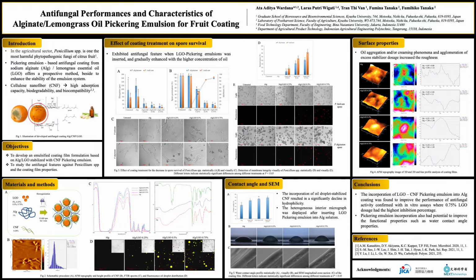Propidium iodide is well known as a fluorescent dye that is able to penetrate dead cells. As seen in figure 3, the result implied that the membrane integrity was impaired by the lemongrass essential oil loaded coating treatment, leading to metabolic disruption and the death of fungi. To know roughness properties, the AFM method was selected. As seen in figure 4, the reduction in smoothness demonstrated in the Pickering emulsion incorporated coating corresponded to the occurrence of oil aggregation or creaming as a consequence of the evaporation step during thin film forming. And it could be observed visually by 2D topography and line profile, in which repeated aggregation was seen forming upland structures.